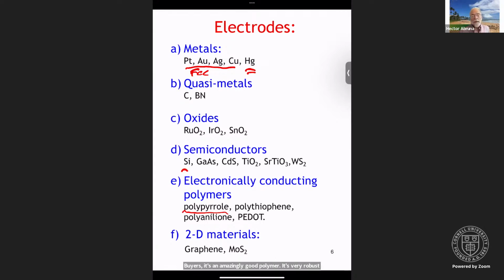More recently, 2D materials, graphene, molybdenum disulfide, molybdenum selenide, etc. What's typical or interesting of these materials is that you can actually have a single layer of these materials. And so then it really begs the question, so what is electrochemistry like when your electrode is basically one lattice spacing in thickness, and the attendant changes in the work function, in the distribution of levels, etc.